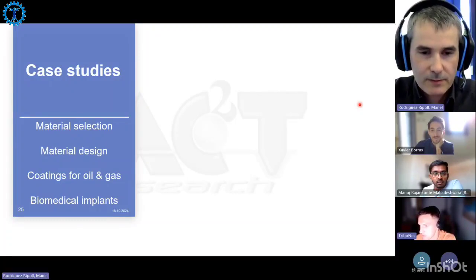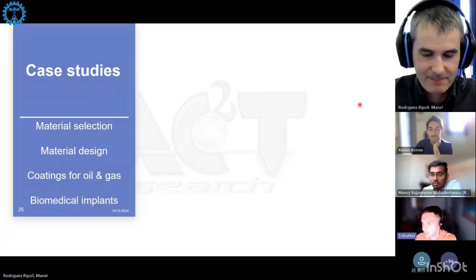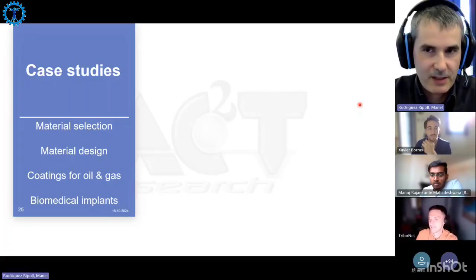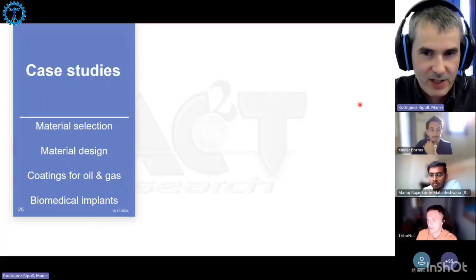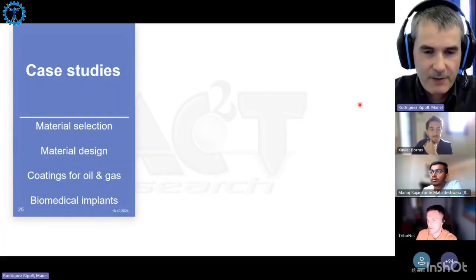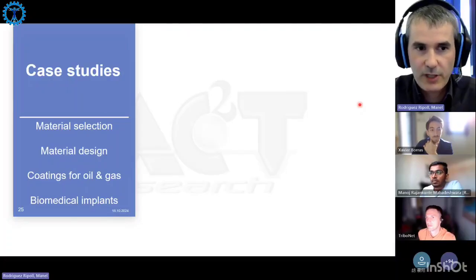So what are the prevention measures for tribocorrosion in ferrous metals? So basically what you need to do is to select a metal that degrades as little as possible in the medium, so that it has good passivation kinetics. And for example, that it's inert. I was doing a review a couple of years ago on coatings for tribocorrosion applications, so thin coatings. And for example, we saw today that titanium nitride has very poor tribocorrosion properties. On the other hand, for example, DLC, which is a more inert material, performs much better under tribocorrosion